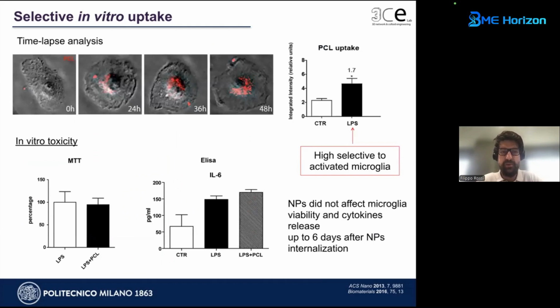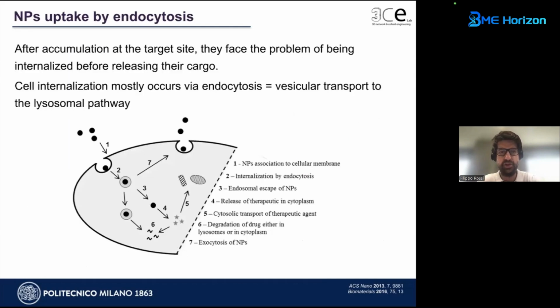With time-lapse analysis, we also studied the kinetics of this uptake. That is very quick: it happens first within 24 and then ends after 48 hours. And considering the balance between control microglia, so not activated, and LPS-activated, we can see a higher selectivity for activated microglia, I would like to add. We proved the biocompatibility with MTT and ELISA tests, so these do not affect microglia viability and cytokine release up to 6 days after the internalization.